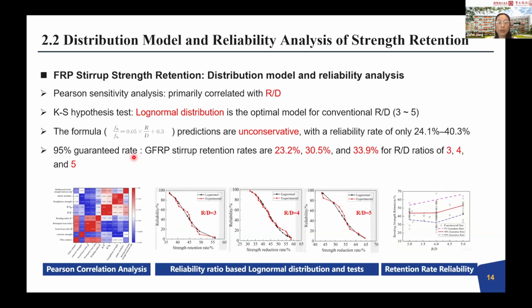We find that this range is commonly used in structures. And also we find that the formula shown here is commonly used in many national codes, in ACI, in Canada, or even in Italy. Their prediction for the strength ratio is unconservative because the reliability rate for this calculated value is only between 20 to 40%. And if we use the data, to make sure of a 95% guaranteed rate for different radius ratios of 3, 4, 5, the ratio will be below 35%. So that is for the reliability analysis.